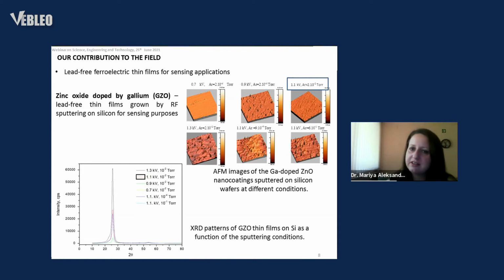Then the positive argon ions are extracted from the fields, accelerated to the target material, for example, zinc gallium oxide, and eject or sputter some nanoparticles or molecules from the materials that are arranged on the surface. But according to the pressure and the voltage, the dynamics and kinetics of the process is different and the deposition rate is different. It could result in different crystallite formations and different surface morphologies.